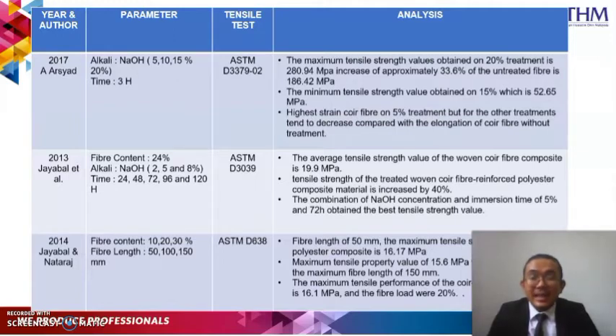In 2013, Jayabalan conducted a study, and the average tensile strength value of woven coir fiber composite is 19.9 MPa. The combination of sodium hydroxide concentration and immersion time of 5% and 72 hours obtained the best tensile strength value.